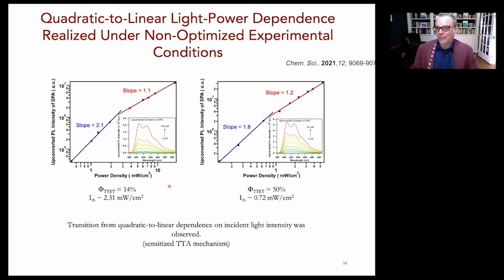And the way we had to do it was, let's move the I value around. Well, how do you move the I value around? Well, you just lower the triplet energy transfer efficiency. So when we dropped it to 14%, we saw that we now have 2.1 and the I value happens about 2.3 milliwatts per square centimeter. When we increase the efficiency up to 50%, we can kind of see we move it to about 0.72. So it goes down in the power plot.